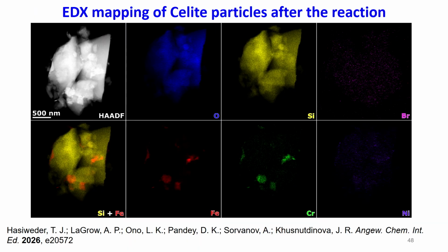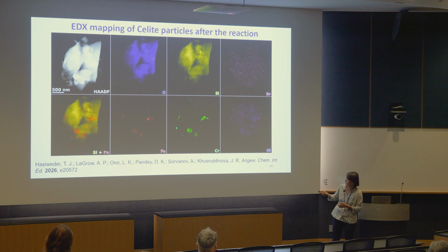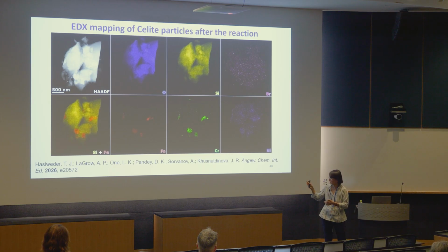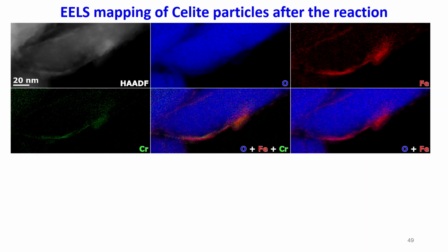We decided to investigate it with the help of TEM and our collaborator, Alec LaGrow, from the core facilities. So we looked at the Celite particles before and after the reaction. I have to say, Celite itself naturally contains a little bit of iron in trace amounts. But after the reaction, we found a big difference. Of course, we still have silicon and oxygen naturally present, but after the reaction, we see these little patches where iron and chromium are co-localized. And chromium definitely was not present in the Celite before the reaction. So where does it come from? And I suppose by this time, the majority of the audience could already guess where it comes from. This is another representation of the same thing: you see again a thin layer covering the Celite particle with iron and chromium co-localized.